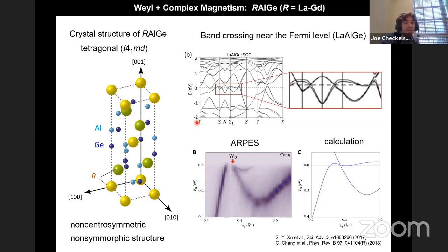However, it turns out in this case, what really seems to be true is that you can understand the bands at the Fermi surface really the same way as the bands from lanthanum aluminum germanium. So there's really not a big difference when you look at the fermiology of those two cases. So therefore, in this particular system, cerium really seems to be important for the magnetism and not as much for the fermiology that is really associated with the Weyl points.